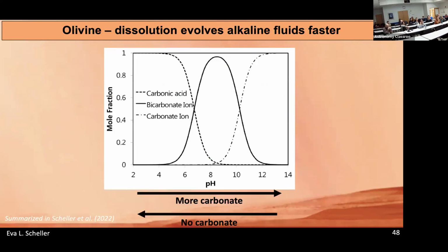So the pH evolution of these fluids is extremely important for carbonates because carbonate anion presence is dependent on pH largely. So if you have a low pH, your dissolved CO2 is going to be in the state of carbonic acid. In the middle, you're going to have bicarbonate. And really at higher pHs is when you get lots of carbonate anion. That's why oftentimes if you have alkaline lakes at pH 10, you're going to get a ton of carbonate. And so if you have faster dissolution, you typically are able to evolve alkaline fluids or high pH fluids faster. And that's something we observe in many earth environments. So there are many, many reasons for olivine dissolution to be great for carbon sequestration.